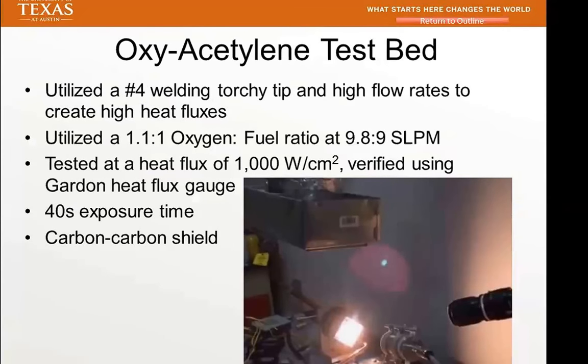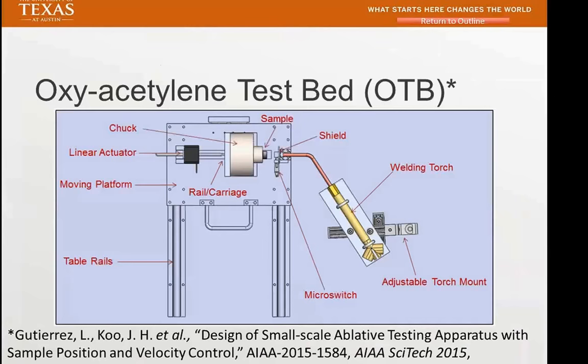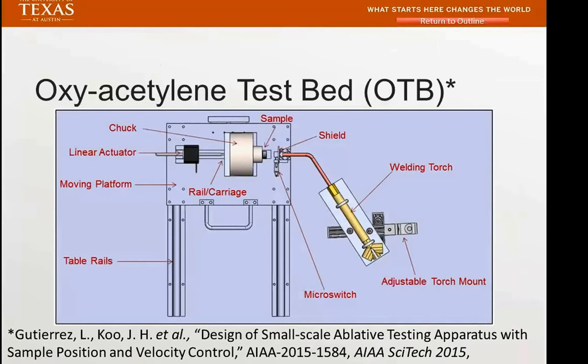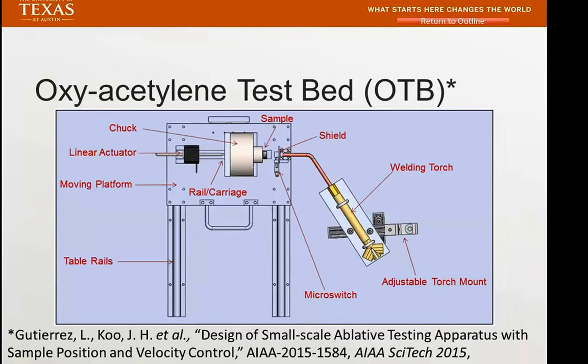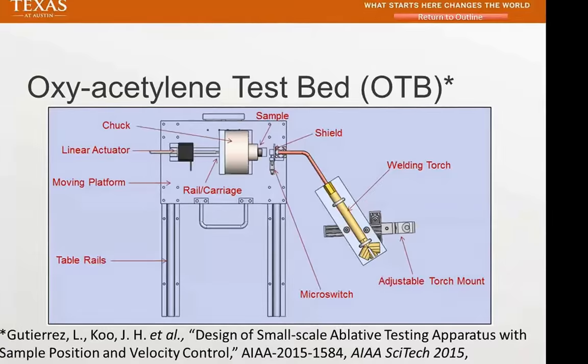So this is what we do using the oxy-acetylene approach. We calculate the fuel ratio as well as measure the heat flux using a Gardon gauge, and we expose using 1,000 watt per cm square and an exposure time. We have a carbon shield actually blocking the flame wrapping around. This is what we did, and this is all presented. These are my capstone team who designed all these, and as with every capstone project, I present a paper, and this was done in 2015 and presented as an AIAA paper.